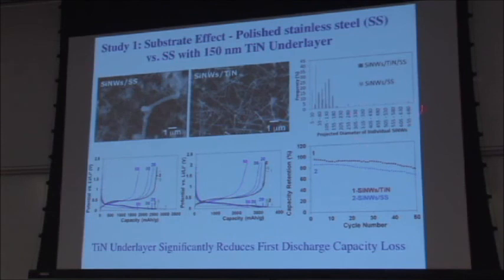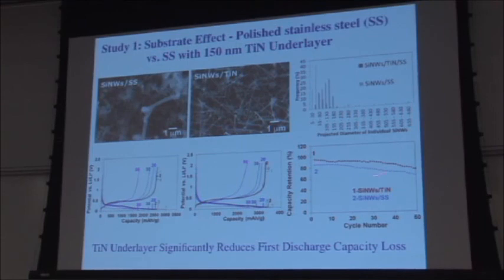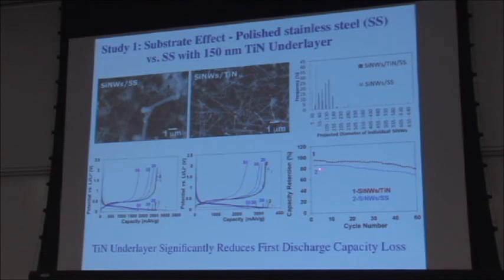It's a very spread distribution on stainless steel. On titanium nitride, it's quite uniform, so you have a fairly narrow distribution. If you look at the capacity retention as a function of cycle number, the degradation is almost identical. But the initial capacity loss here is about 5%. Here, it's about 15%. Actually, it's more than 15%, so you have a huge difference. I think this is maybe 17%. You have a huge difference in the initial capacity loss.